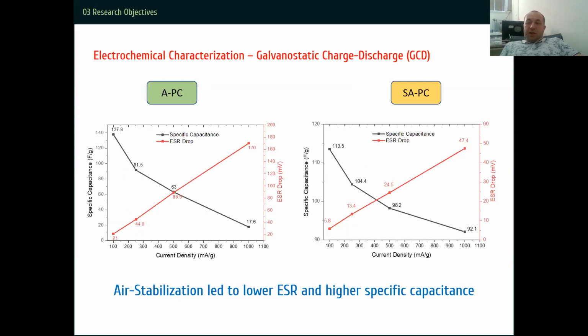To summarize the specific capacitance and see the equivalent series resistance ESR values, the ESR value and specific capacitance versus current density were graphed. As expected, the specific capacitance has decreased with the increasing current density, and the ESR value has increased with increasing current density due to the high current flowing on the activated carbon surface. And we can say that the air stabilization technique led to lower ESR and higher specific capacitance at high current densities.